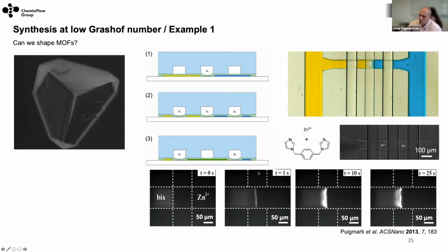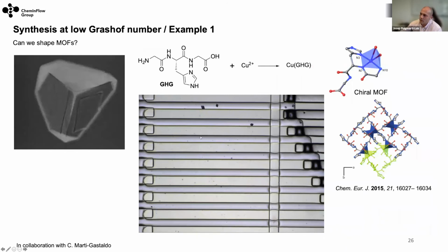As soon as we open the valve, what we see is that the coordination polymer is generated really at the interface of the two. And then, of course, because of the diffusion coefficient, one will move faster, and you have the formation towards the imidazole container. So what this clearly shows is that, in fact, it's true. With this kind of approach, it's possible to achieve this free interface diffusion process. So why am I introducing this? Because under these conditions, we can have this low Grashof number. And this is what we did now with this metal organic framework.